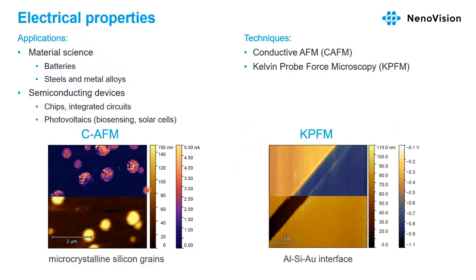Another electrical property is the surface potential, which we can measure using Kelvin probe force microscopy. Here is a reference sample of aluminum, silicon, and gold interface. And so we can see the different surface potentials because they are different materials.